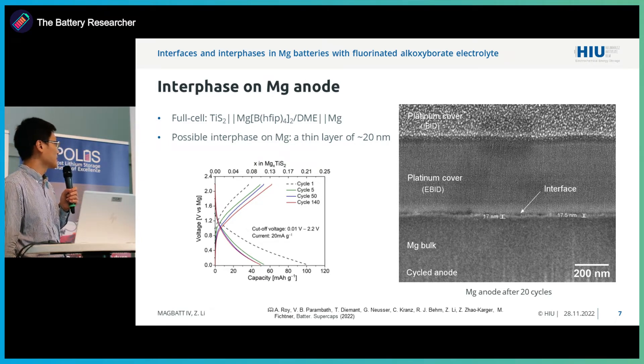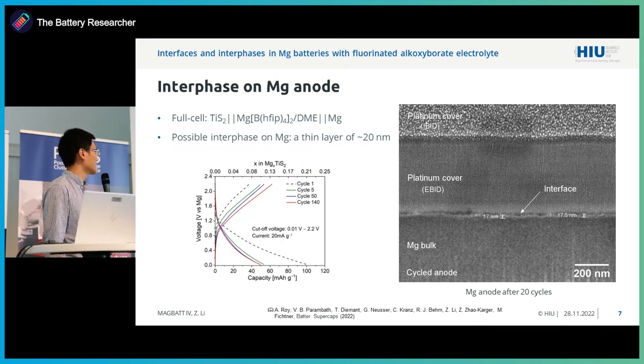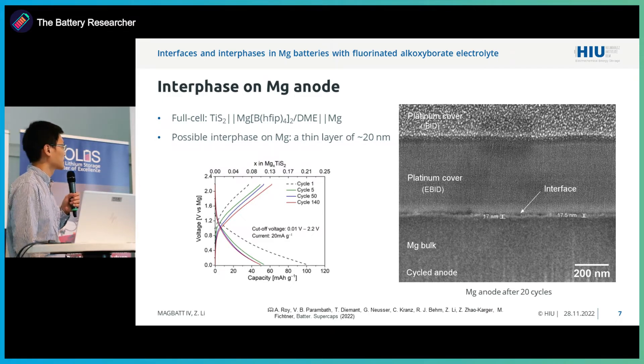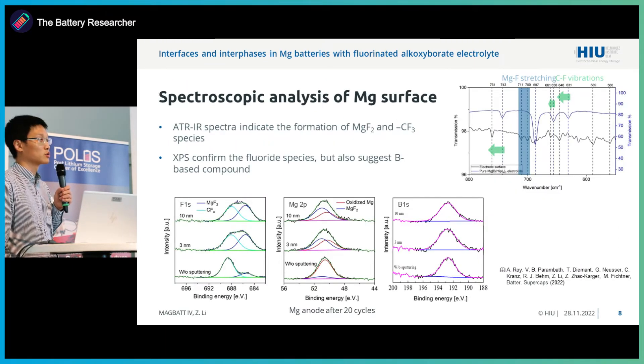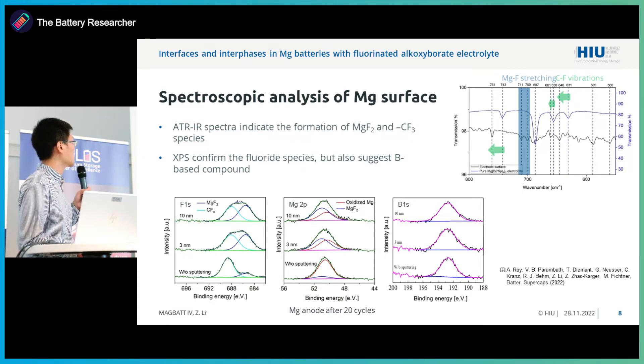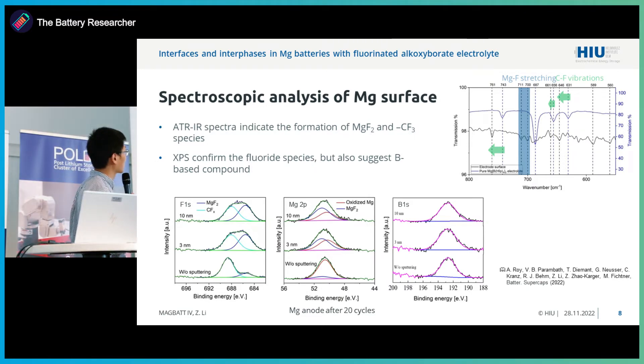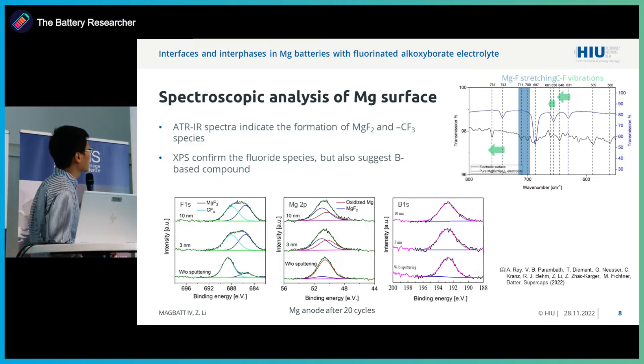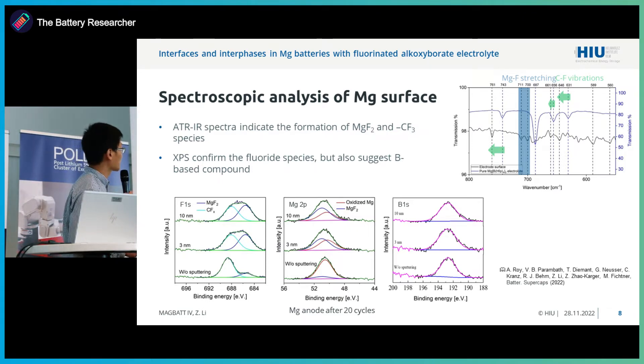What we observe is some interface layer of roughly 20 nanometers, and we wondered if this is really an SEI interface layer. However, at that time the SEM had reached its resolution limit, so we were not able to go further in that direction. Instead, we used spectroscopy analysis to study what is going on at the magnesium surface.